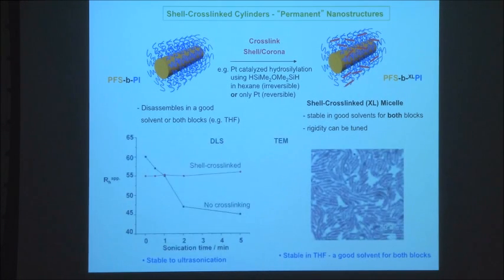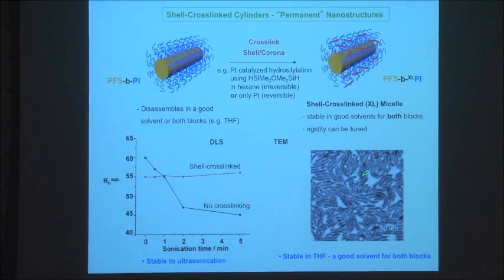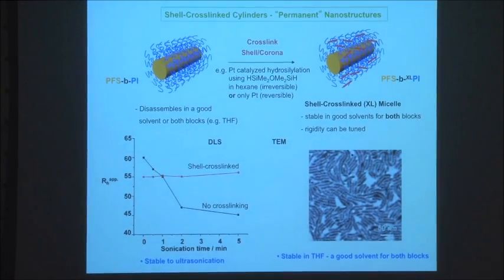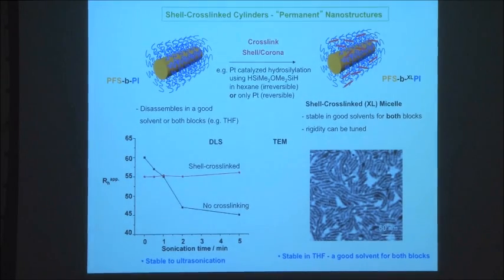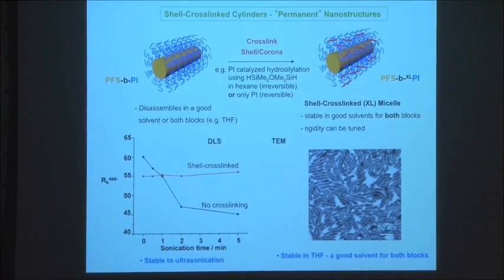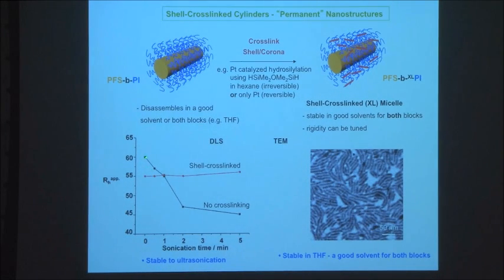So how is the stability of these structures? Well, if you take these materials now and put them in a solvent that's good for both blocks, you retain the structure. So these are now permanently stable, as you can see here. Once you've cross-linked them, they're much more stable structures. If you sonicate the uncross-linked micelles, they will decrease in size. You can show this by dynamic light scattering. But if you cross-link them, they don't change their size at all. So these are very stable. If you have no cross-link, if you take long cylinders and sonicate them, they break up. And this is something we'll actually use very, very shortly in this lecture.